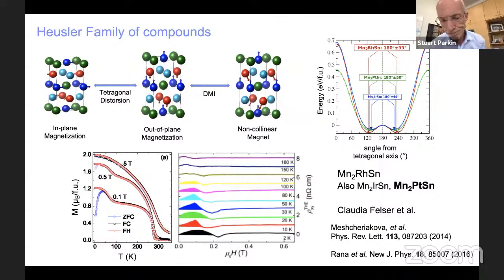ferrimagnetic system. This system typically has Curie temperatures above room temperature. And shown on the bottom, you can see that in low magnetic fields, the magnetization undergoes a transition at approximately 100 degrees Kelvin in Mn2PtSn, where the structure goes from the simple ferrimagnetic structure to what is believed to be the non-collinear magnetic structure shown in the cartoon on the top. And this was some work that was published in 2014.